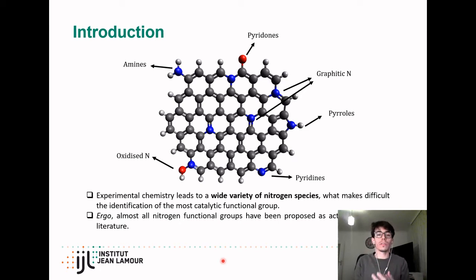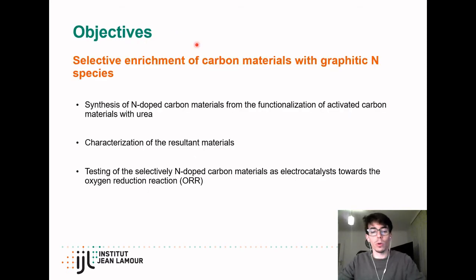And as a consequence of this fact, almost all nitrogen functional groups have been proposed as active sites towards the oxygen reduction reaction. Inspired by all these problems, the main objective of this work consists of the selective enrichment of a pristine activated carbon with only one nitrogen functional group, graphitic nitrogen species. As specific objectives, the preparation of these nitrogen-doped carbon materials from the functionalization of activated carbon by using urea as a nitrogen precursor, the characterization of the resultant materials, and finally the testing of these nitrogen-doped carbons as electrocatalysts towards the oxygen reduction reaction.